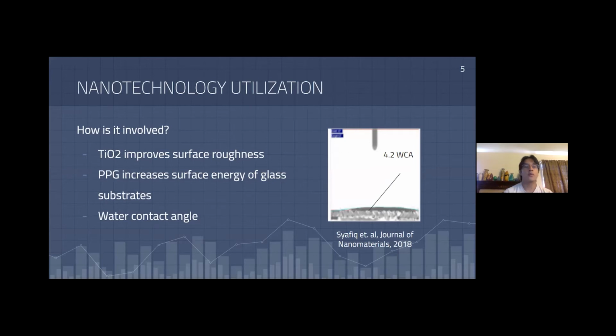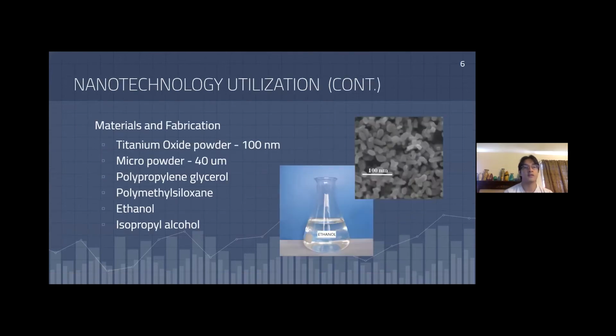And so we're going to be using a journal paper as the basis for our fabrication process and materials. It studies super hydrophilic coatings for all transparent glass by Syafiq et al.. And so the materials for our solution are going to include titanium dioxide powder of 100 nanometers and also micropowder of 40 micrometers. And then PPG, or the polypropylene glycol, as a hydrophilic agent, and the polydimethylsiloxane, or PDMS resin, as a surface modifier. And then other materials include dissolving agents such as ethanol and isopropyl alcohol.